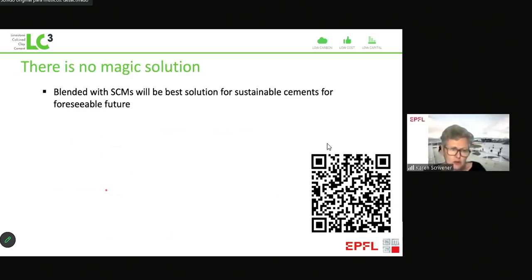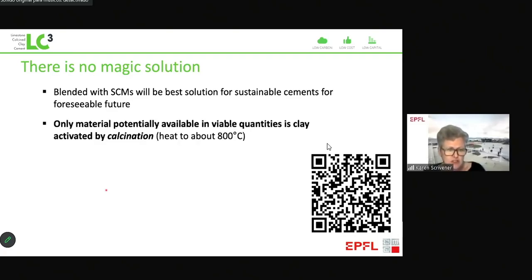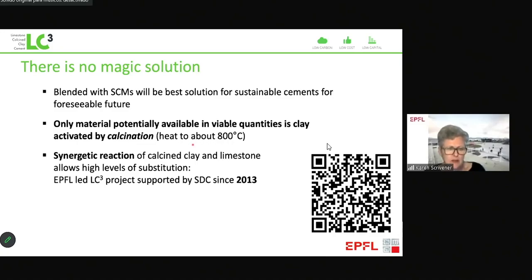So there's no magic solution. Blended cements with supplementary cementitious materials will be the best solution for sustainable cements for the foreseeable future. And the only material available in viable quantities is clay, which can be activated by calcination, that's to say heat to about 800 degrees. And what we discovered, which is the essence of this LC3 technology, is there is a synergetic reaction between the calcined clay and limestone, which allows you to go to very high levels of substitution.